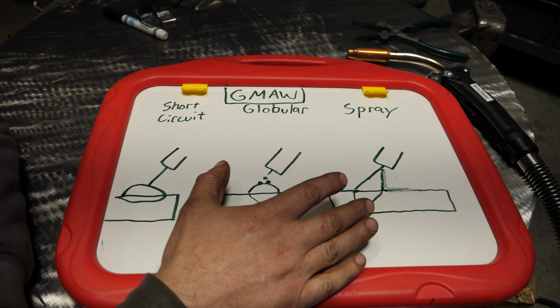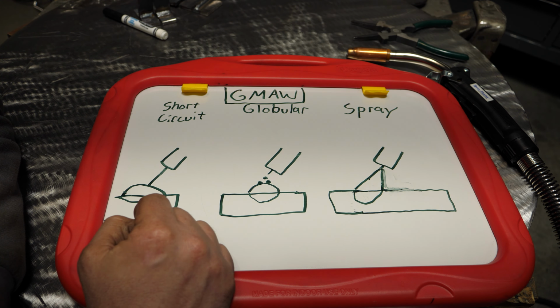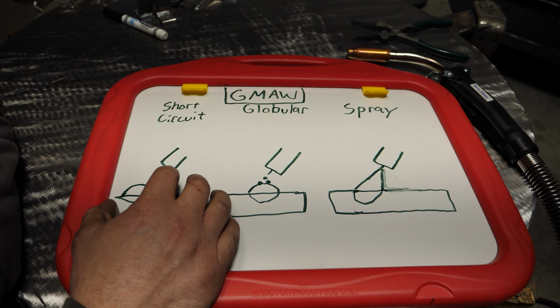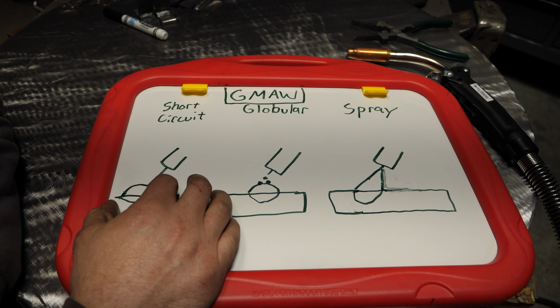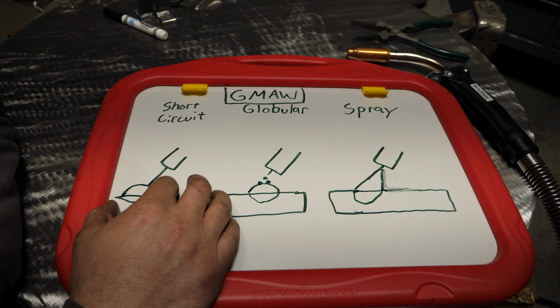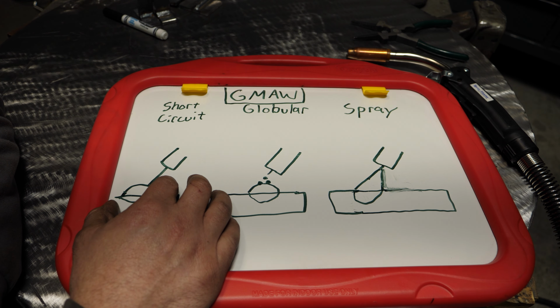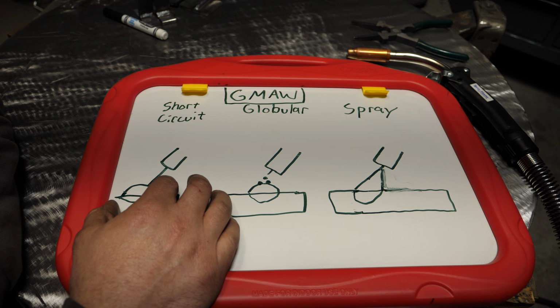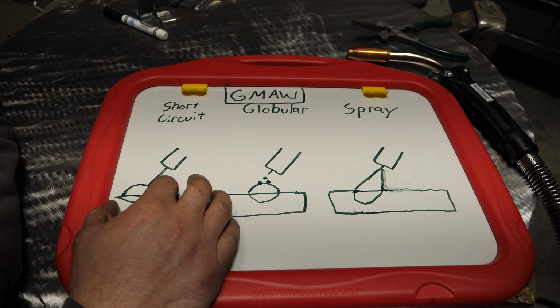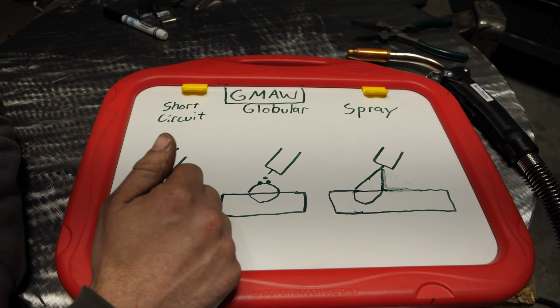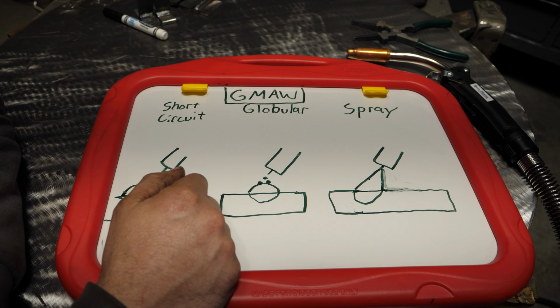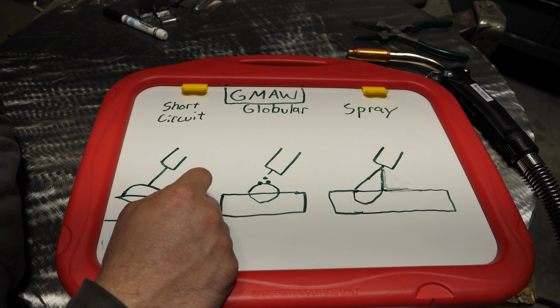Now, with all of that said, the last thing I'm going to say is that when you're welding in short circuit mode and you attempt to weld very thick plate, you wind up with fusion issues because it doesn't carry enough heat with it. And no matter what you do, how much you crank up your welder, you're still going to have fusion issues, especially when you start talking half inch plate.